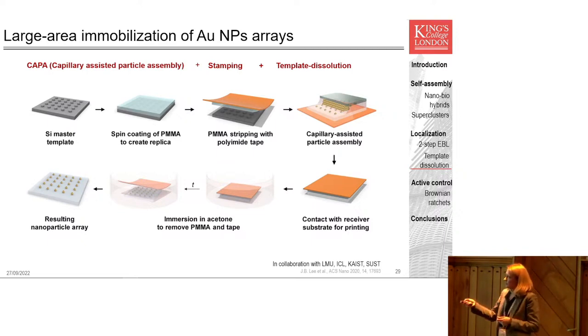So the way it works is you start with a silicon master template, which then you spin coat PMMA on at fairly low thickness and low concentration, which allows you to very carefully then strip an inverse of the design with a simple tape. You can then deposit nanoparticles using gold into the holes of this template, and then you take this tape and press it against whatever substrate you desire and place the whole thing in acetone, which is then dissolved, hopefully leaving nanoparticles on the surface.